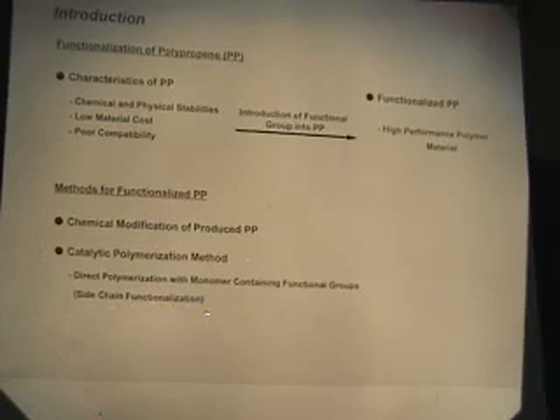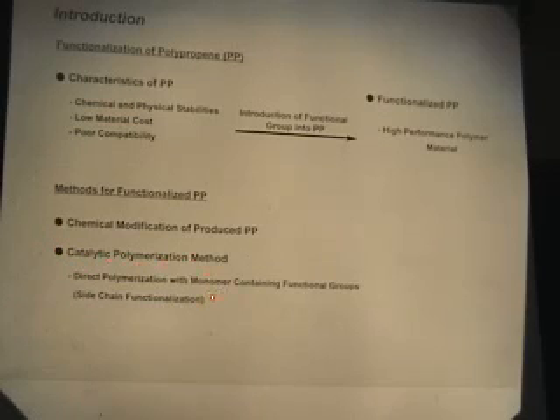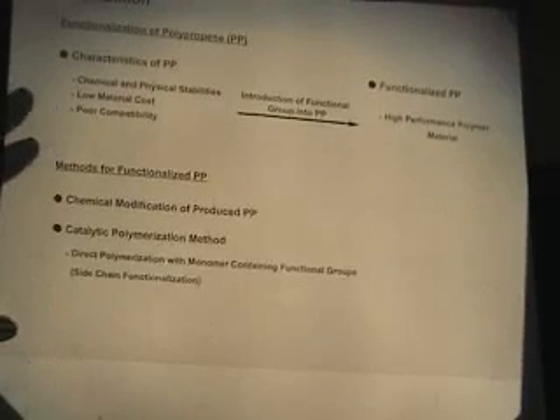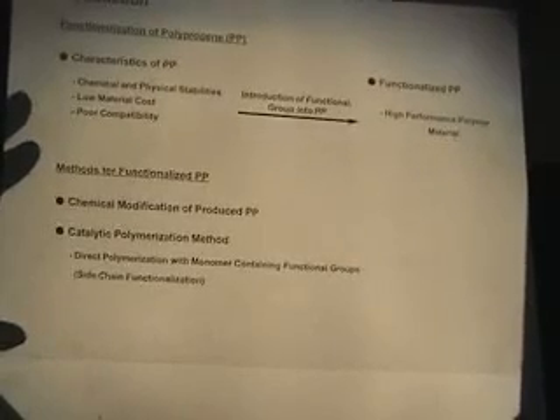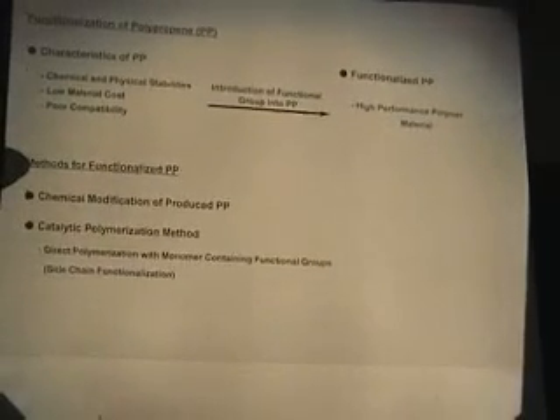The common methods to produce functionalized polypropylene are chemical modification of the produced polymer and direct polymerization. Chemical modification of polypropylene is very difficult under mild reaction conditions. In many cases, side reactions such as degradation and cross-linking occur during the modification reaction. In the catalytic polymerization method, the active site of the catalyst is intolerant to the functional group of the comonomer. This is the disadvantage of this method.